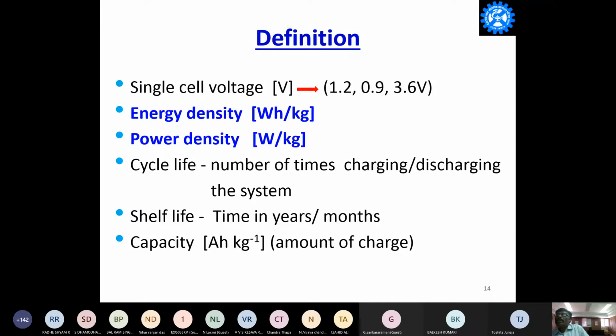Now another thing is power density and energy density, which I will explain at the end. The cycle life is the number of times you charge and discharge your battery. For example, if you charge at night and discharge during the day, that is called one cycle. All lithium ion batteries can last for 1,000 cycles, which means you can use them for 3 years. The shelf life is if you assemble a cell and keep it on the shelf for 10 years, nothing will happen to lithium ion batteries. But with some primary cells, the electrolyte will come out. You might have seen in your penlight cells, after 1 year, the electrolyte comes out. So this is called the shelf life, and the capacity is denoted by ampere hour per kilogram, which is the amount of charge that can be stored.